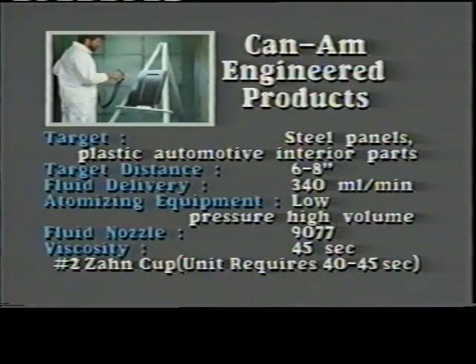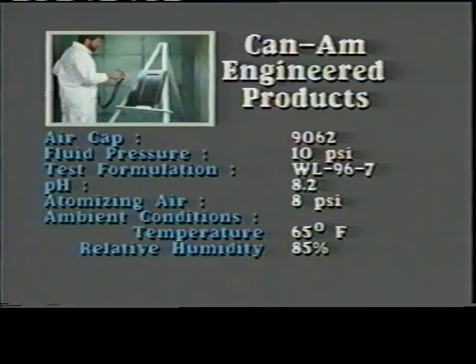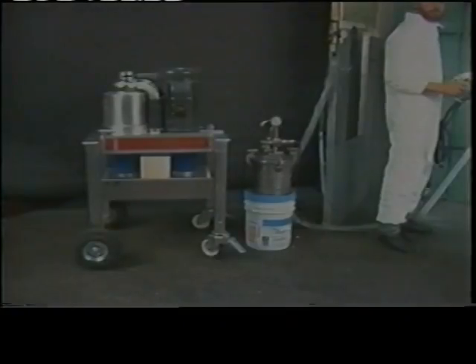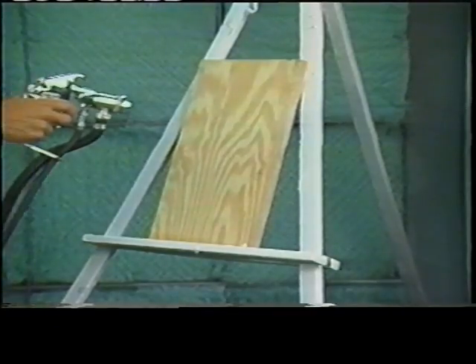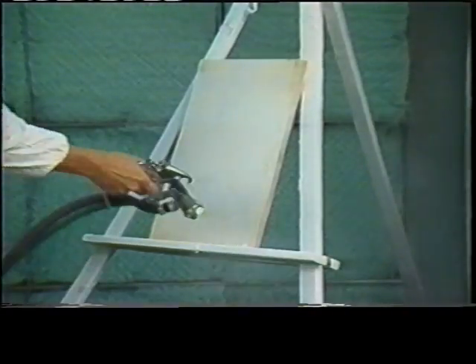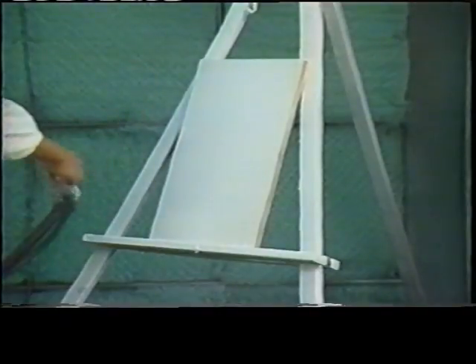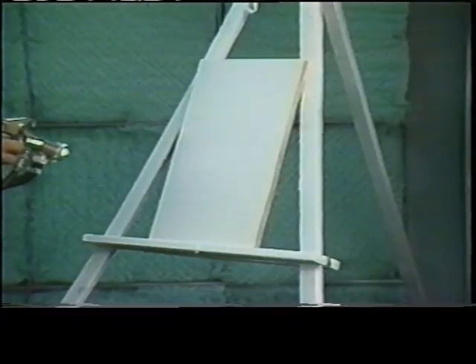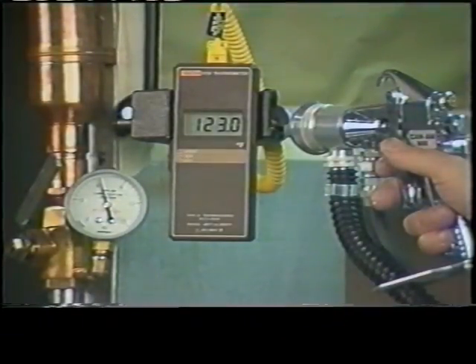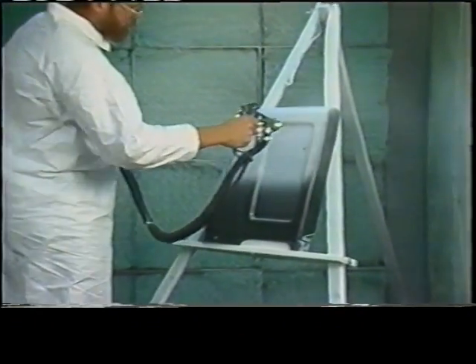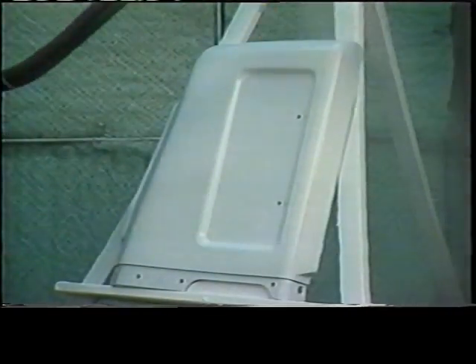Can-Am Engineered Products tested a low-pressure, high-volume applicator, a special type of air atomizing spray unit. In the Can-Am trial, technicians employed a low-pressure, high-volume system. Of the 3 air atomizing units, this piece posed the most severe challenge to the waterborne coating. The continual discharge of hot atomizing air from the applicator creates a warm, arid environment in which the coating can dry very rapidly. To compensate, Can-Am reduced the test lacquer's viscosity to 45 seconds, lowest in the 5 trials.